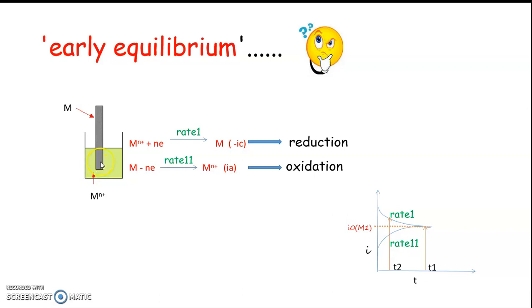the deposition and dissolution start, as I said earlier, and there may be two processes. If I take an acid solution, sulfuric acid or hydrochloric acid, where there is H plus ion formation, and I dip a metal into it, the first process starting should be the reduction process, since there is more concentration of H plus ions in the solution and not on the surface. After some time, the cathodic rate, the reduction process, diminishes and the dissolution reaction starts with rate 2. It is represented in this graph. At equilibrium, both attain the same rate and we get an exchange current density at time t1.